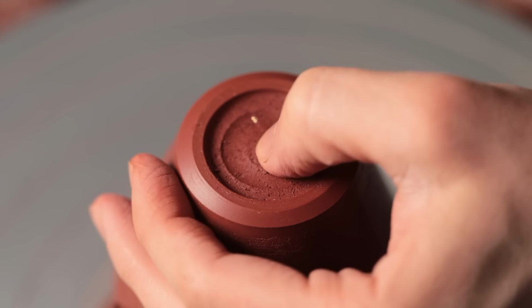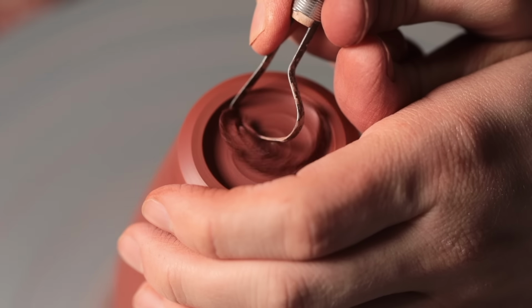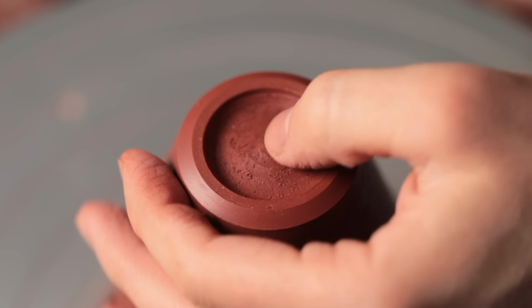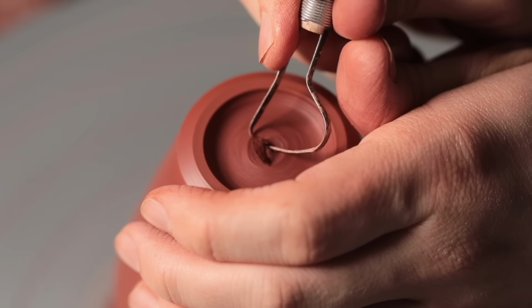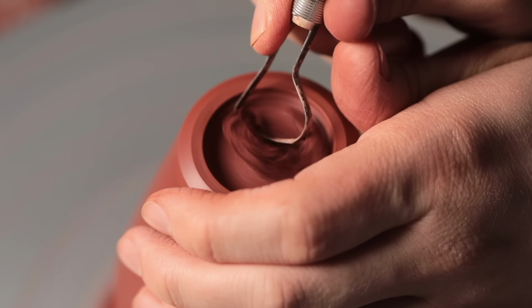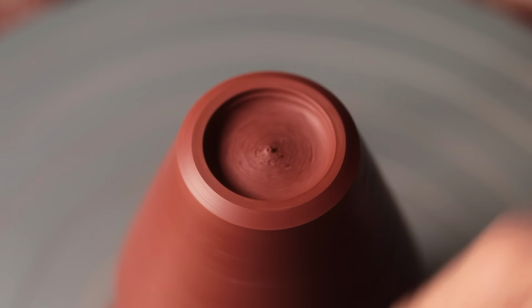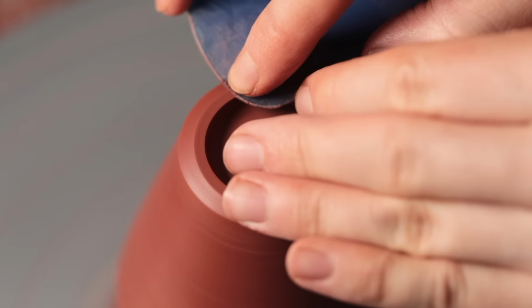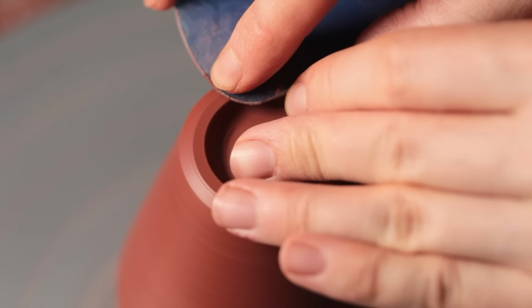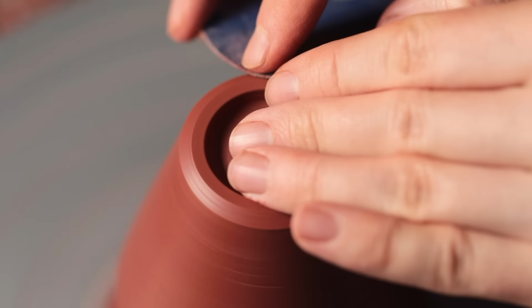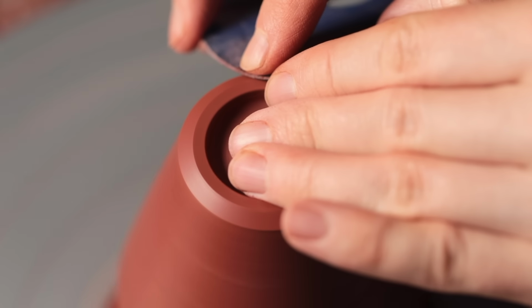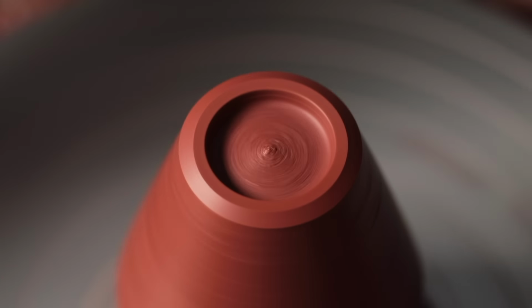You can see one of the bronze filings here, and those that are more present on the surface, as opposed to being buried within the body, will ultimately melt into much larger specks of metal on the surface of these pots. I then burnish the foot, pressing the smooth side of this plastic kidney against it, which is especially important for the foot, as this is going to be the only part of exposed clay on the entire piece.